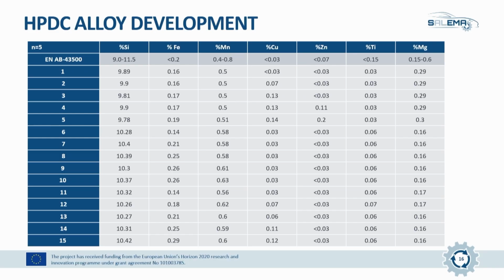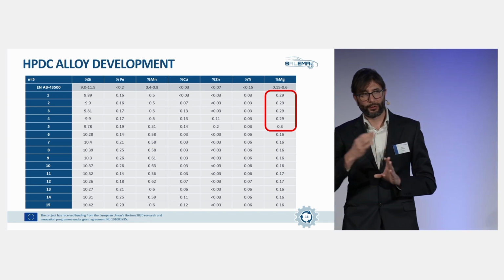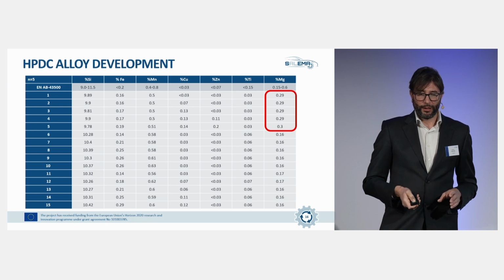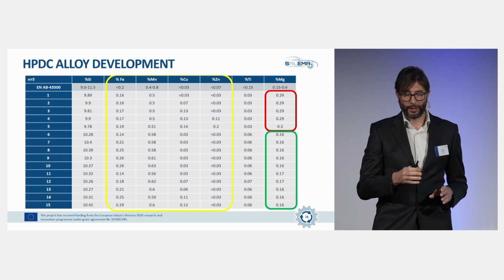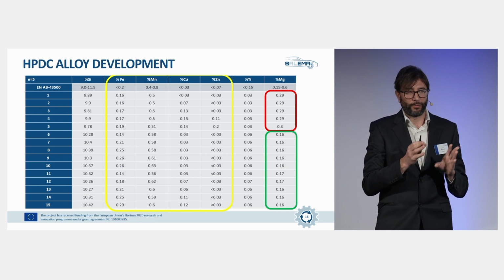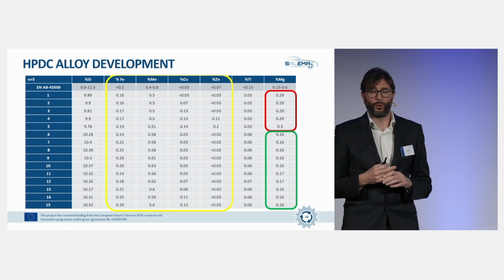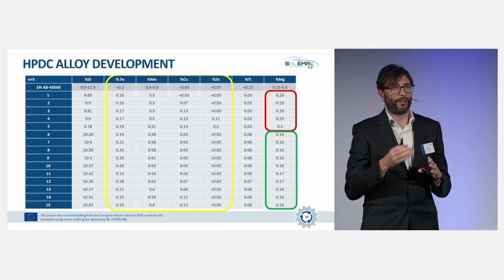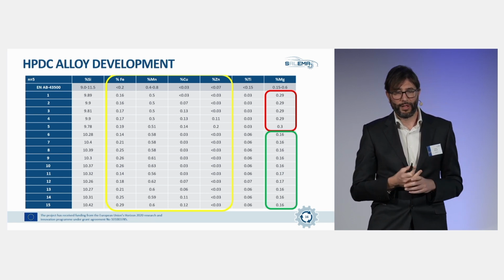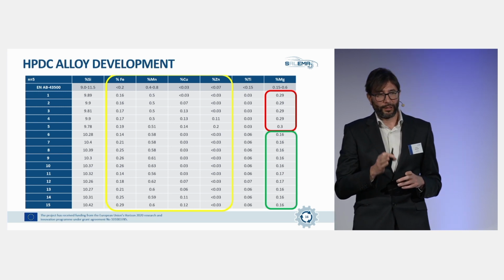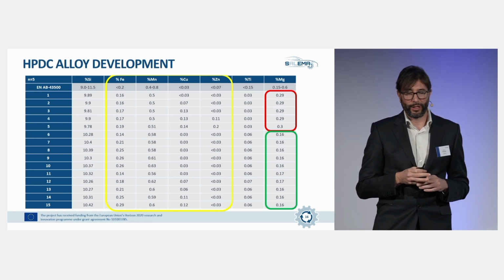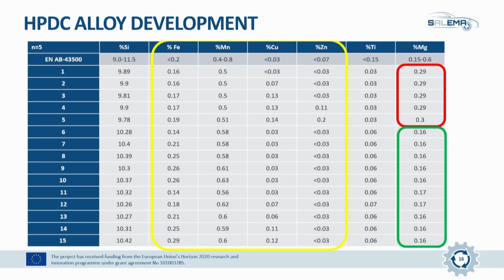So for instance, for high pressure die casting, on the development of alloys with high recycled component, we work on 2 levels of magnesium, a medium, moderate level, about 0.3, and a low level, in order to get better ductility. And then we change the amount of impurities, focusing on the ones that, together with the industrial partner, the aluminum producer, we found as the most restrictive in terms of being able to get this alloy from scrap. That is mainly iron and copper. Also, zinc could be a limitation, so we tried what happened if we increase it. And we change slightly the amount of manganese, going to 0.5 to 0.6 in some alloy variants. Okay.